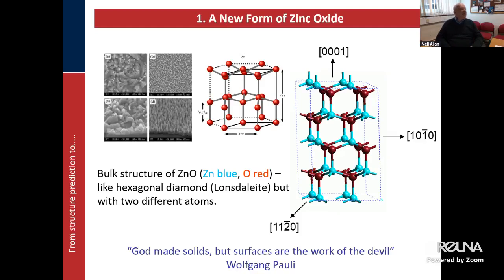Well, we started off, and two students of mine were working on these surfaces, and we did thin films, and using GGA density functional theory back then, they were optimizing the structures of the films. And when it came to this 0001, what happened is that the structure changed very, very hugely. And I said, I don't believe it. I mean, the bulk structure of zinc oxide has all the atoms in tetrahedral coordination, with the zinc tetrahedrally coordinated and the oxygen tetrahedrally coordinated, in a structure called the Wurtzite structure.